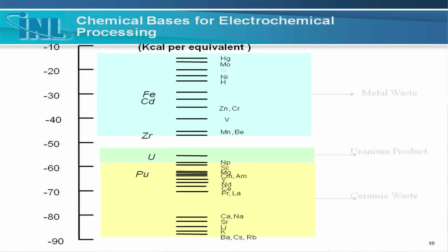Similar, these are grouped together and go into other areas within the process, and then you have all the actinides that basically are lumped together. So what this basically says is, if you take spent fuel and dump it into a chloride salt, these things down on this end of the spectrum tend to like to form chlorides. So if you dump spent fuel into a salt bath, these things will tend to react with the salt, form chlorides, and stay in the salt.